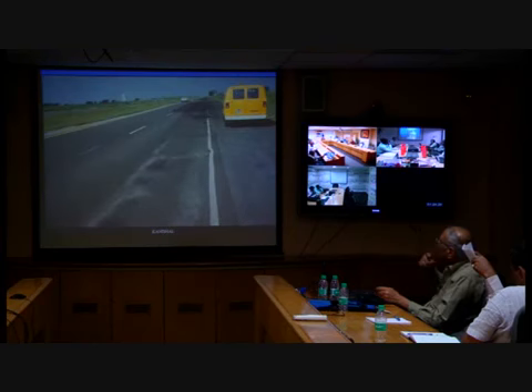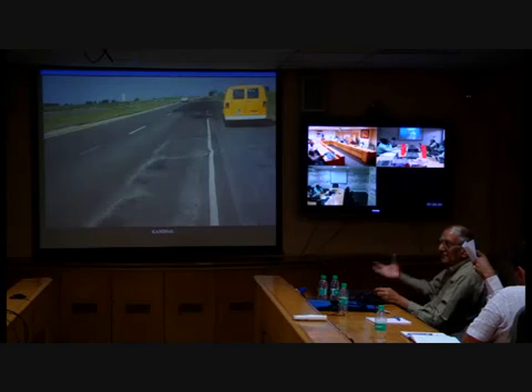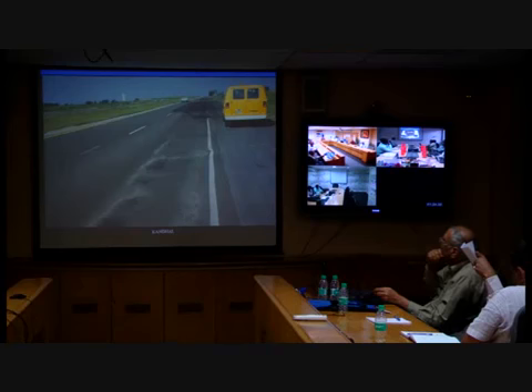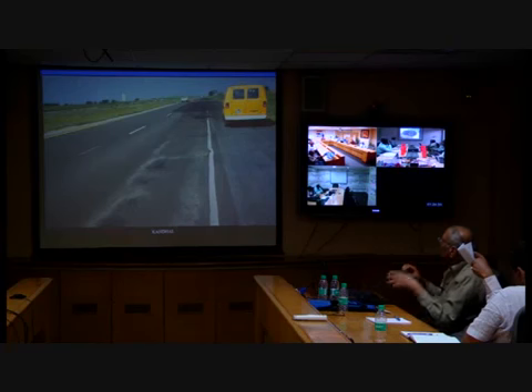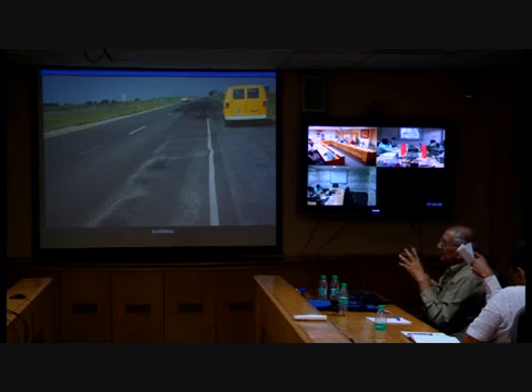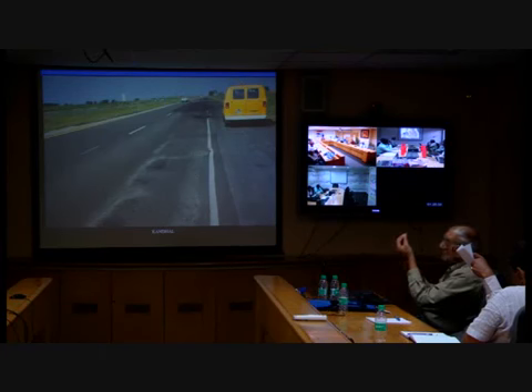One typical, classical set of stages of stripping, which doesn't happen on all projects, is that first the DBM will start to strip. Somehow the moisture is coming from the bottom up, like from WMM, it's going up. So first its effect, the DBM will start to strip. Strip means the bitumen film has been stripped off the aggregate. The aggregate looks like a clean aggregate. So what we see on the surface, the first stage, is some white fines. We see fines with white color because in the DBM the stripping has taken place. So the aggregate has some dust coating or whatever. The moisture will bring that dust to the top surface of the BC.